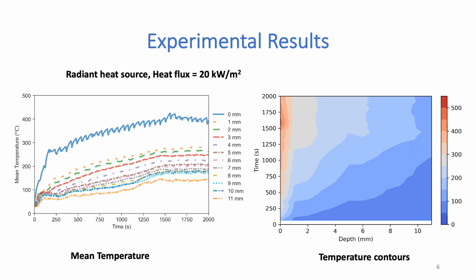The experimental results we show in a couple different ways. So we took temperature readings internally of the drywall every 1 millimeter into the drywall. There is one that's mounted on the exterior, the heated side, and this is the blue line. That's the 0 millimeter mark, and it's the highest temperature on the chart, which is expected. And then we go every millimeter into the thickness of the drywall from there.